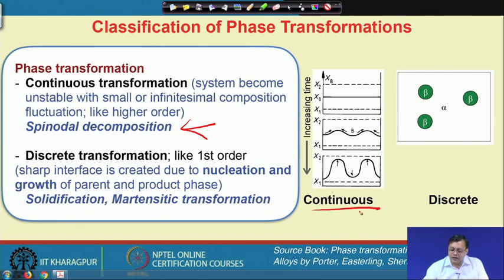In this particular diagram, you can see that x 0 is the average composition of a solid solution, and there are solute atoms which can segregate in some localized regions, like here and here. Let us say a B type of atom in A. So, that basically segregates somewhere, and there is always a net decrease of the free energy by a small composition fluctuation, which finally leads to higher and higher fluctuation, and it always destabilizes the system.